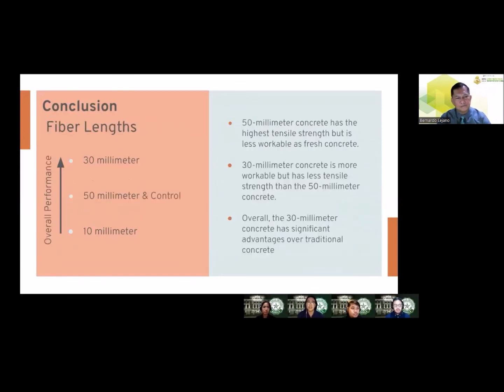Since the difference in compressive strengths is minor, workability and split tensile strengths are the main metrics of comparison. The results show that 50 mm concrete has the highest tensile strength but is less workable as fresh concrete and has the lowest compressive strength. On the other hand, the 30 mm concrete is more workable and has the highest compressive strength, but has less tensile strength than the 50 mm concrete. Overall, the 30 mm concrete has significant advantages over traditional concrete.